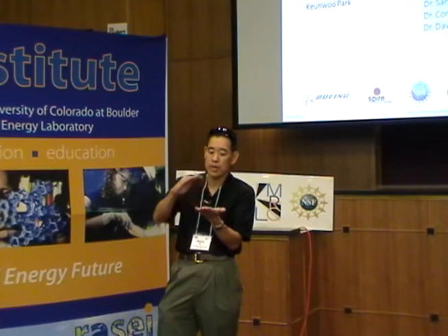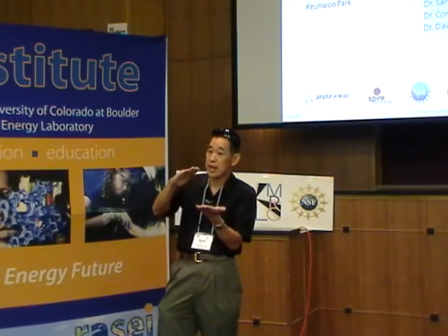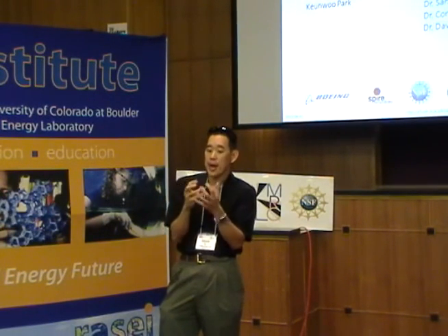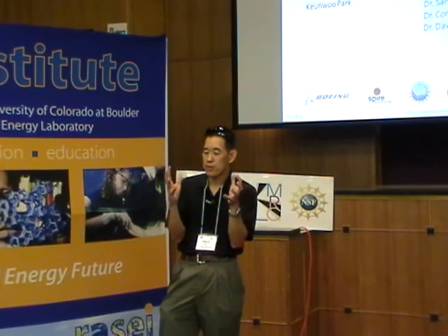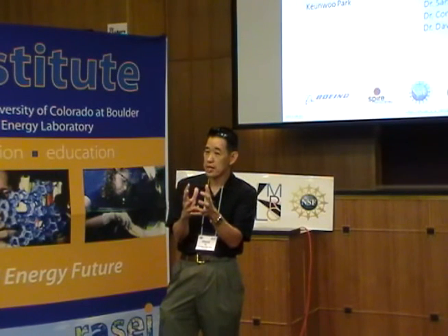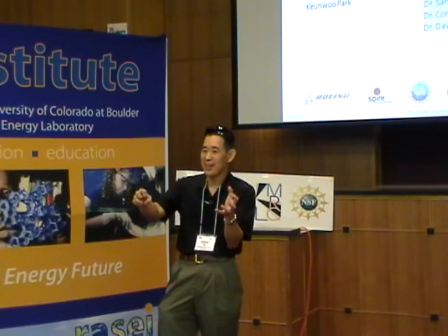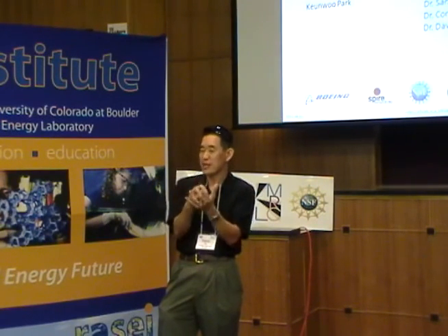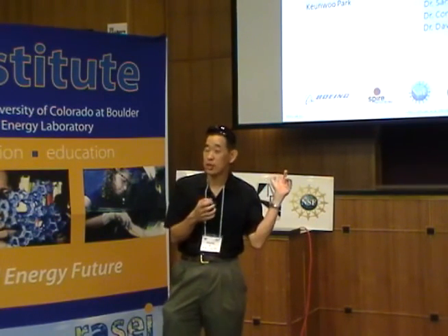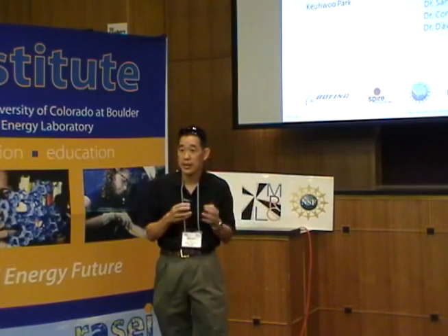When you're growing quantum wells, you're just modulating the composition and it remains planar. You can also engineer the growth process such that if you deposit just pure indium arsenide, then it'll form clusters, or islands, rather than a planar film. And then if you bury those, that looks like a quantum dot. So that's essentially what those structures are.